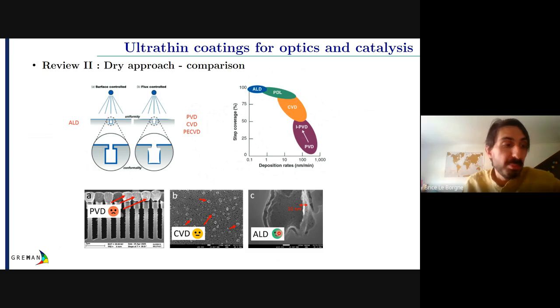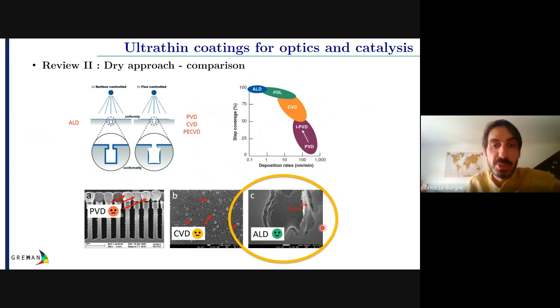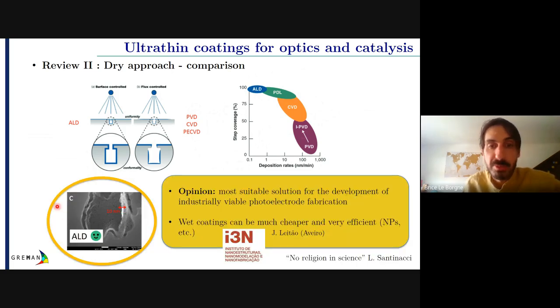Here you have some examples of why ALD can be nice for porous silicon. Here you have high aspect ratio trenches in a device. With PVD, you clog the pores and you can't really have good pore filling. CVD would clog porous silicon. That's something we've done in our lab. And when you use ALD, you can nicely coat the pores down to the bottom, which is not so easy. So of course, I'm going to focus my work on the use of ALD now. And I think this is one of the most suitable for industrially viable photoelectrodes.